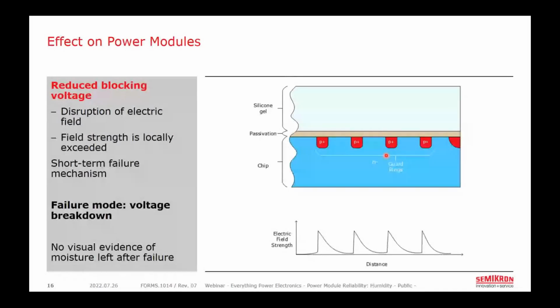So point one back there, we discussed how moisture can cause corrosion over time and eventually lead to chip failure, and that you can see some evidence of that corrosion. But there's another way that condensation or even just water vapor, that is high humidity, can reduce the effectiveness of the voltage blocking structure around the edge of the chip. This diagram here shows the cross section of the edge of a chip, with the center of the chip towards the left and the edge of the chip over here towards the right.